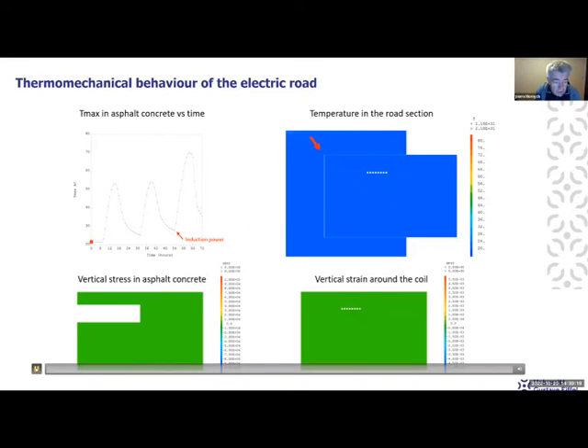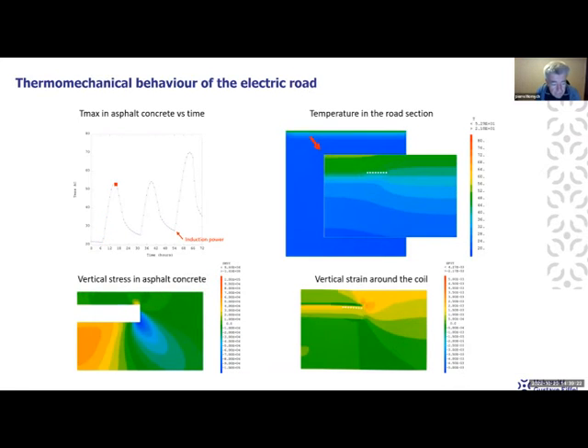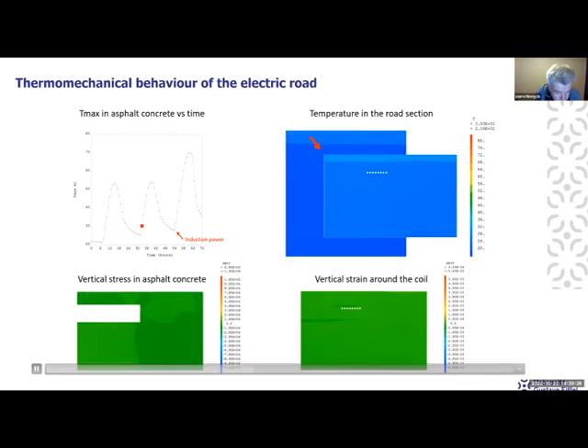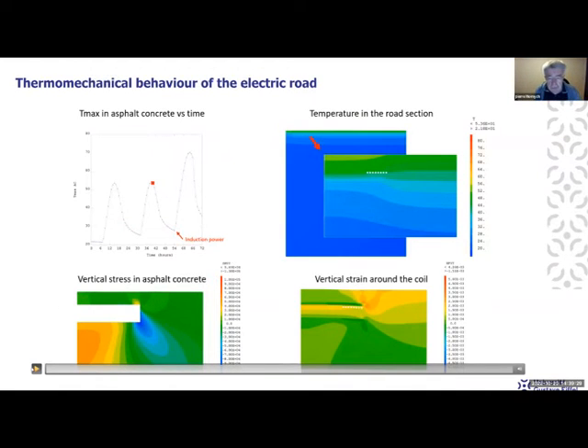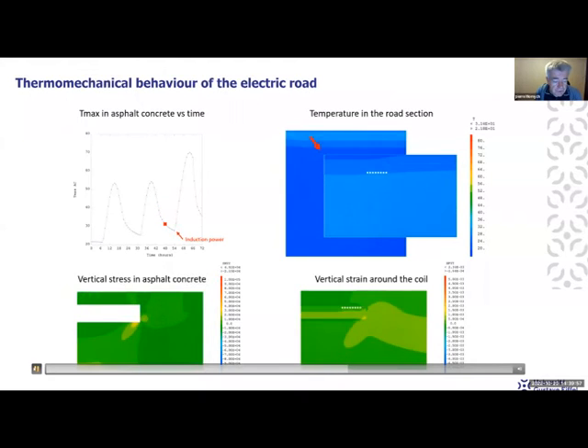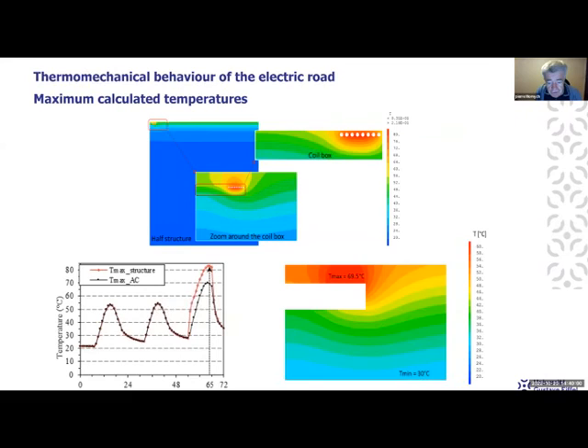So here you can see what happens when the temperature varies. So if I can try to stop it, sorry. You can see that when the temperature increases, here it's only the pavement temperature, you generate higher temperature near the surface. And because the thermal properties and the thermal dilation properties of the coil and of the asphalt concrete are different, you generate stresses and strains, in particular at the interface between the block and the pavement. And when you add the inductive charging, the temperature increase is higher. And so you exacerbate the phenomenon, you increase the stresses and strains, and you increase the temperature.